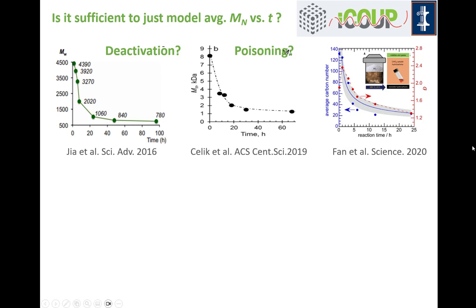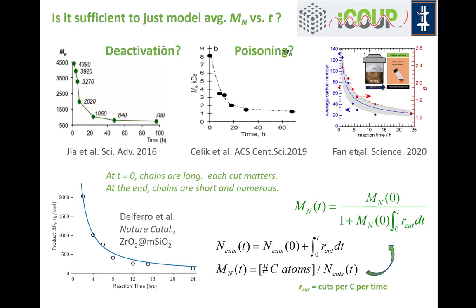In the supporting information of the Science paper, you can begin to see a derivation of what's happening. The gist is that at the initial time, all your chains are long and there aren't very many of them, so each cut matters in the molecular weight distribution. At the end of the process, the chains are very short and there are a lot of them. If you're cutting at the same rate, most of the time you're just cutting a short chain, which doesn't make much difference in the average.